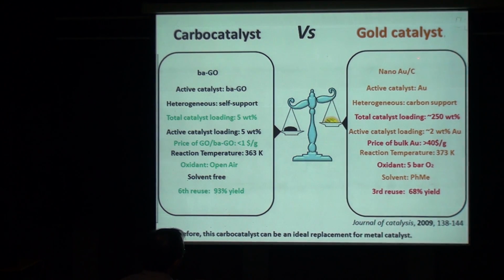In this case, we do not need to use gold. We just use the BaGO, which is graphene oxide, no gold, just this alone. And the catalyst loading is only 5 weight%. And you compare the price versus gold, compare the oxidant, we use open air.